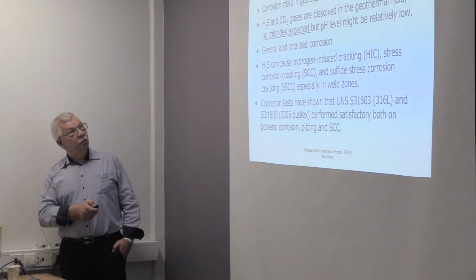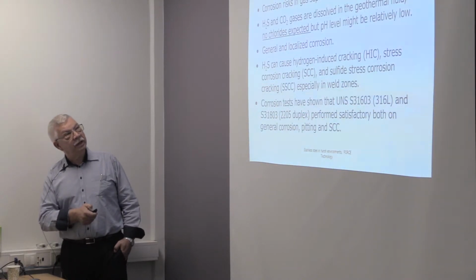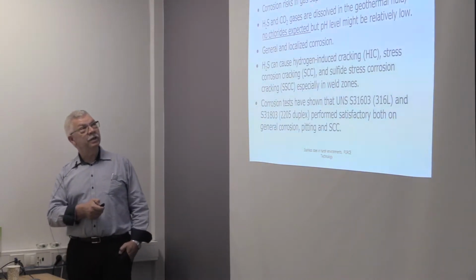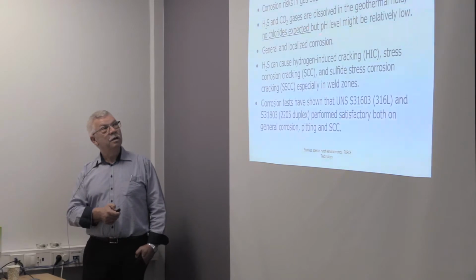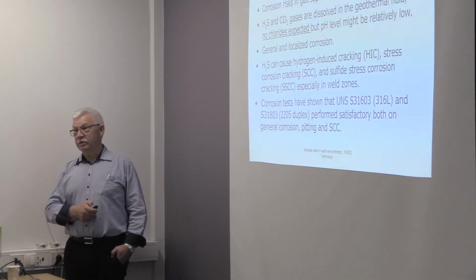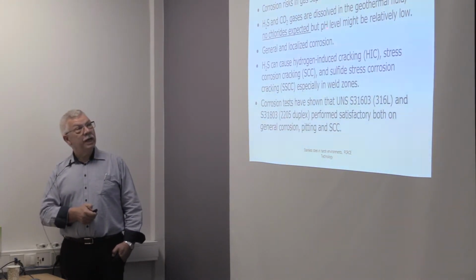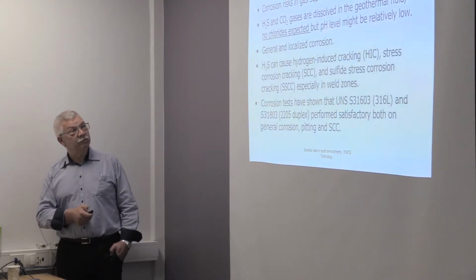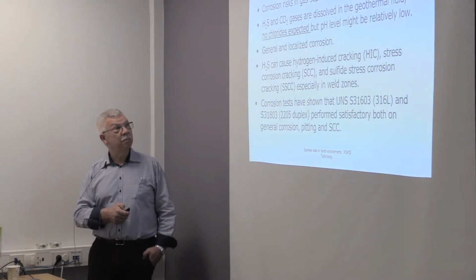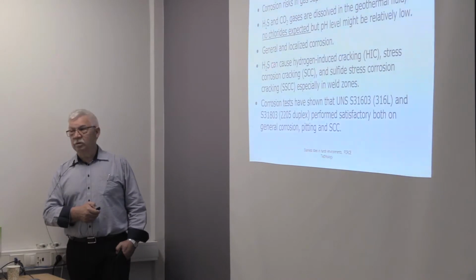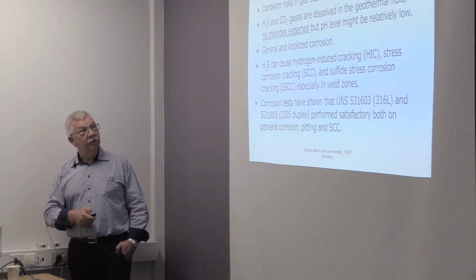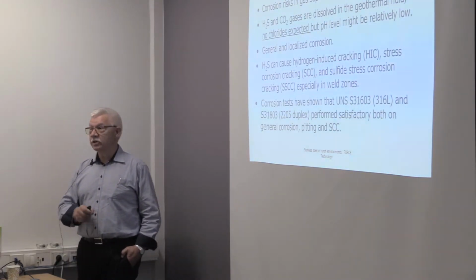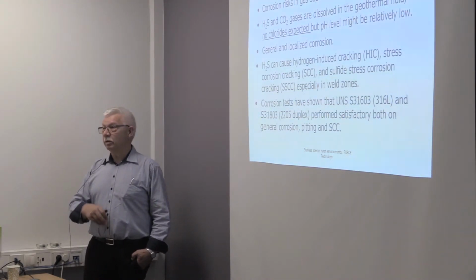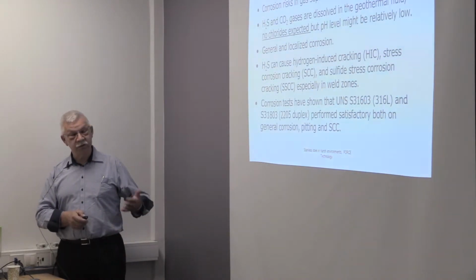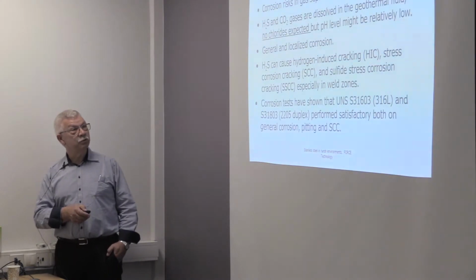From another source, in a materials performance research project done, I guess, here in Iceland, on corrosion risks in gas separation systems, where we have H2S and CO2 gases dissolved in the brine, but which is good for stainless steel, there are no chlorides in this solution. The pH might be relatively low. The risk that we have to address is whether there will be general or localized corrosion. With the H2S, we might consider whether there will be a risk of hydrogen-induced cracking, but that would only be for martensitic material. That's only for hardenable materials that we can risk that. So if we go for stainless steel or austenitic stainless steels, we will not see the hydrogen-induced cracking.